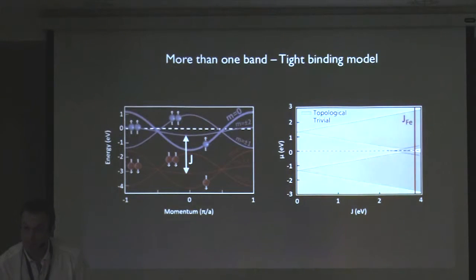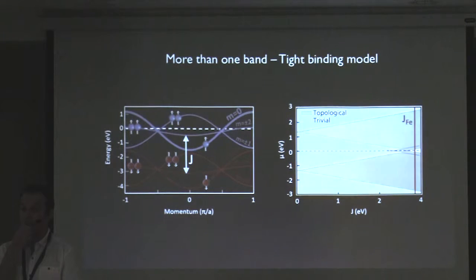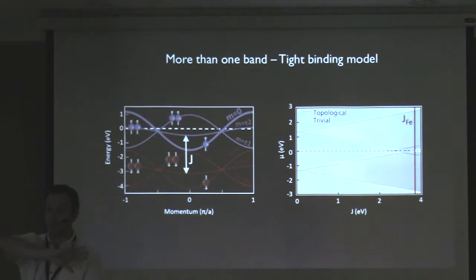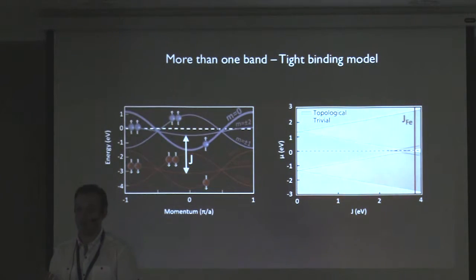Regarding the exchange coupling: in our case, the atoms are ferromagnetically arranged — we just measure that. Without the superconductor, there is already spin splitting between the chain atoms, and J is extracted from DFT calculations. You put the atoms on the surface and from the DFT calculation you extract an effective J. It does depend on the Fermi level of the metal, but you have that from DFT, and in principle you can study this as a function of various parameters.